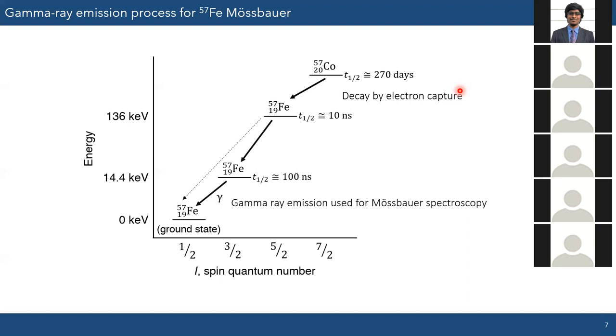So if I'm trying to run some 57 iron Mössbauer spectroscopy ahead of time, I need to buy some 57 cobalt, and within less than 270 days, probably run my experiments? Somewhat. That is its half-life. Over 270 days, the amount of 57 cobalt will have decreased by half, so you'll still have a reasonable amount of 57 cobalt to undergo decay. However, if you want the most gamma rays going out, you would want to use it as soon as possible.